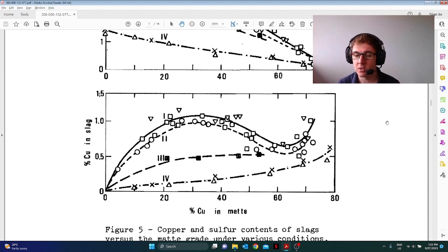So what happens is that when you've got a very pure iron oxygen sulfur system, you don't have that oxysulfide split. You've got a completely miscible oxysulfide phase. Under the right conditions, you can split them out into two separate molten phases, a slag and a mat phase. And that split is enhanced by adding things like copper and other base metals to stabilize the mat, and on the slag side stabilize it with silica. And so you get that split and separation. It gets stronger under certain conditions.